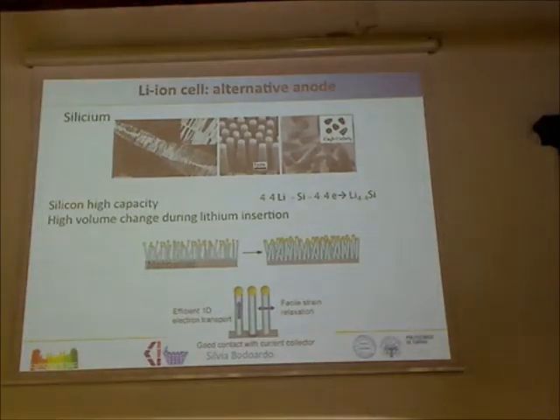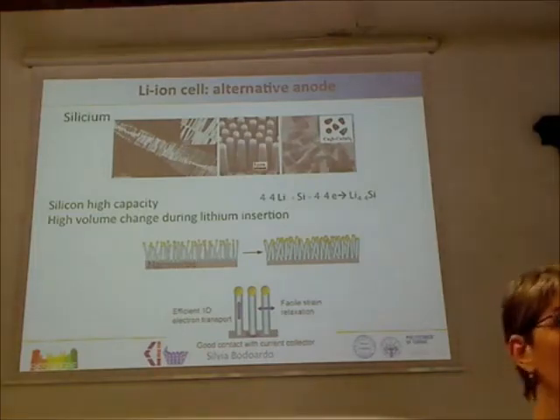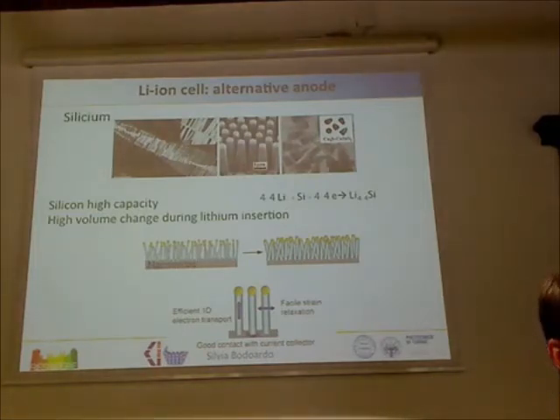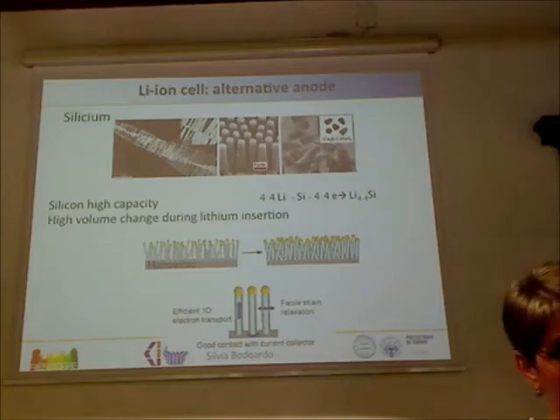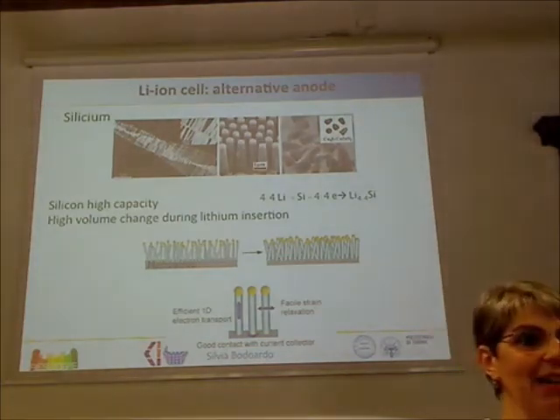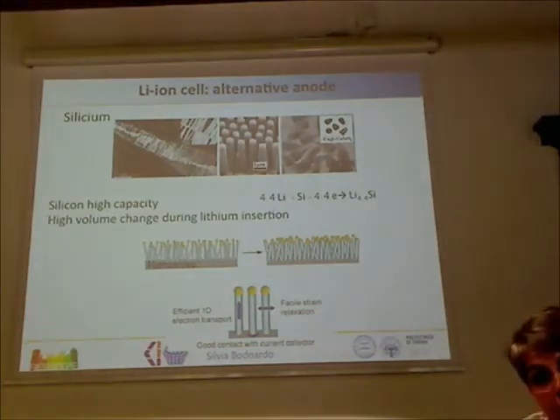For example, silicon. Silicon has a big problem. It's very good to store lithium ions. It can store a very big amount of lithium ions, reducing. But the problem is that it changes volume while it's forming the alloy with lithium. So it means that when you have one small particle, its volume increases so much, many hundreds of percent, that the electrode cracks and it breaks.